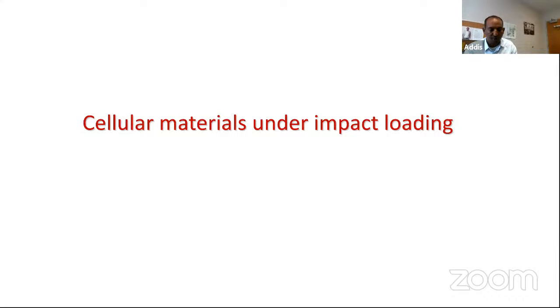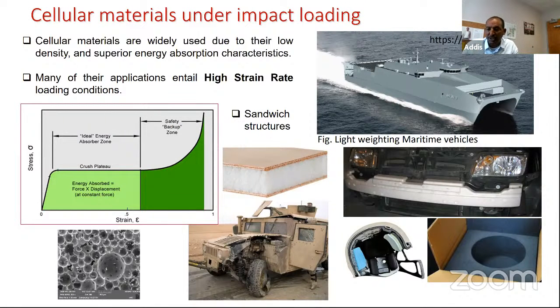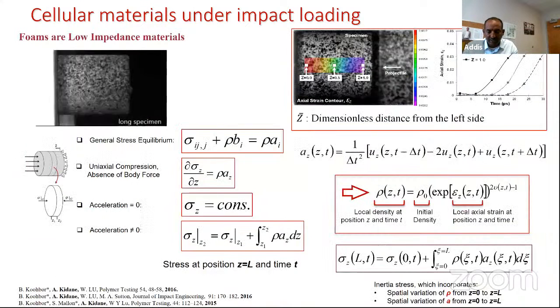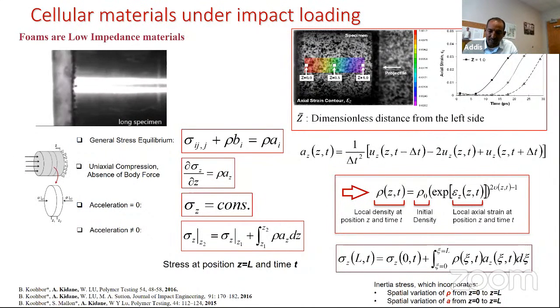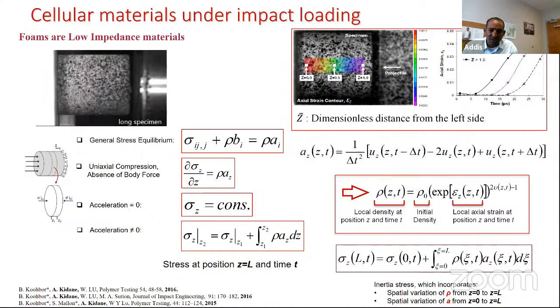Some of the examples I'm going to show you are not new to the community. For example, cellular materials under impact loading conditions. These materials are known for energy absorption and are applied for structures subjected to high strain rate loadings, such as Navy ships, helmets, and others. The reason is that these cellular materials have large deformation and a large area where they can absorb energy. There has been a lot of interest in developing such materials with higher yield stress, but also increasing this energy absorption. Unfortunately, until today, even though there are a lot of computational as well as experimental techniques, the practical design is based on empirical formulations.